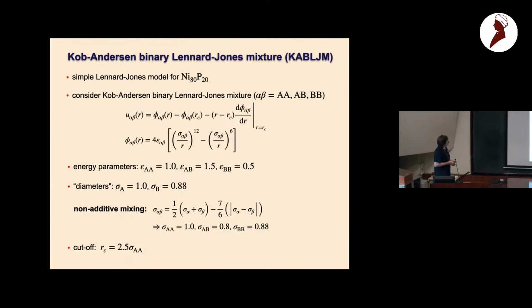What I use throughout my talk here is the Kob-Andersen binary Lennard-Jones mixture. This is a binary mixture, 80-20. It was originally seen as a model for nickel 80, phosphorus 20. These are the energy parameters, and you have a non-additive mixing rule here, which one can write like this.